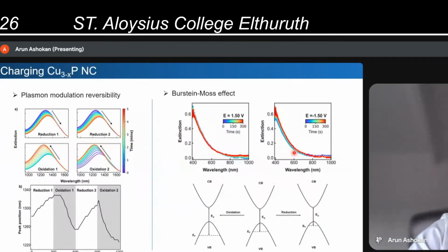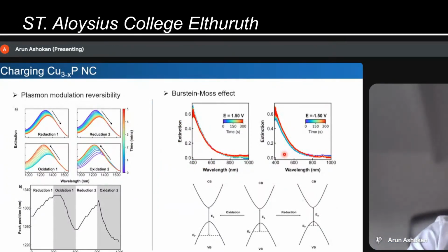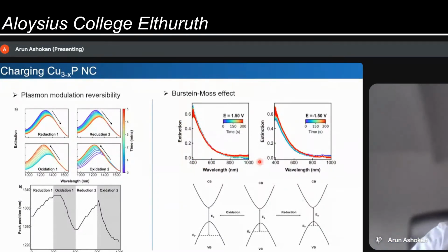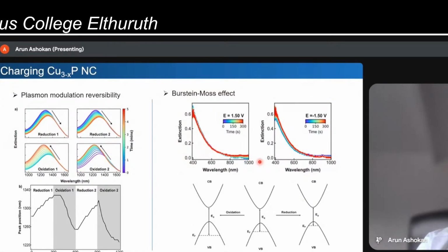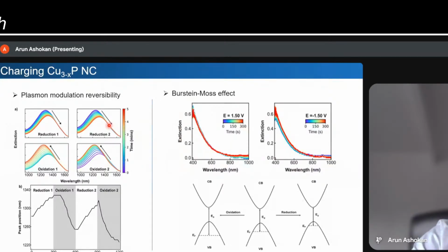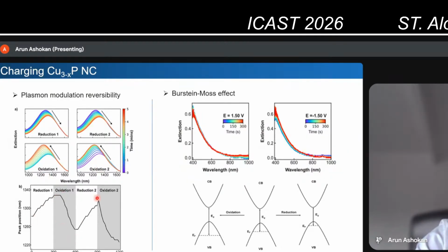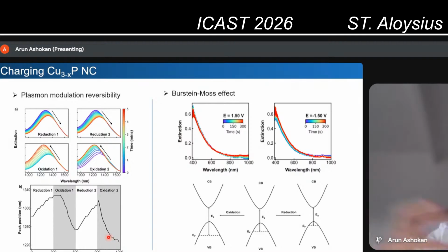And if you want to use this for any application, you want to test the stability, you want to see whether this plasmon peak can be modulated at different cycles. So we just tried two different cycles, one reduction followed by one oxidation, and another reduction followed by another oxidation. You can see that the plasmon peak can be reversibly tuned by applying the oxidation and reduction potential.